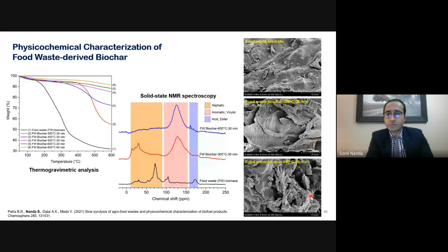Now, these are the scanning electron microscopy images of the food waste, which you can see here on this figure. This is the untreated food waste. It shows almost a very rigid and a very intact structure. But when the biochar produced at 300 degrees Celsius and 600 degrees Celsius was examined, you can see that the structure of this biochar shows more disintegration when it was generated at even higher temperature. We also did a BET surface area analysis of the biochar produced at 600 degrees Celsius and 300 degrees Celsius, and we found that the biochar produced at a higher temperature tends to have a higher surface area and porosity because of the liberation of these organic residues and devolatilization and generation of more porous and graphitic or aromatic carbon in the biochar.